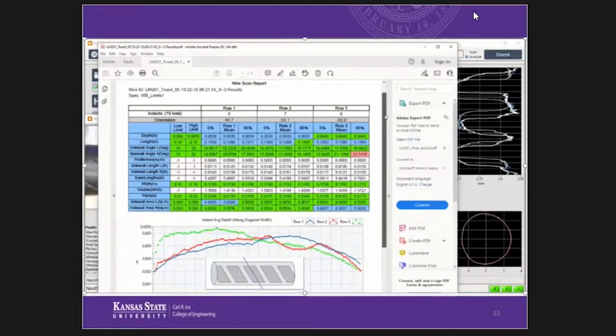Also, the green, this particular row of indents, the average, it shows a big skew to one side. So this indent is a lot deeper on one side compared to the other. That means the indent roller is either wearing, or likely we have a bearing starting to go in one of the wheels, or it's not in center. So all this comes out quickly.